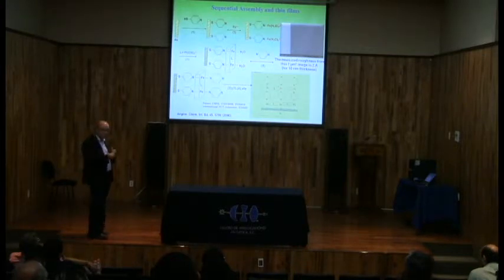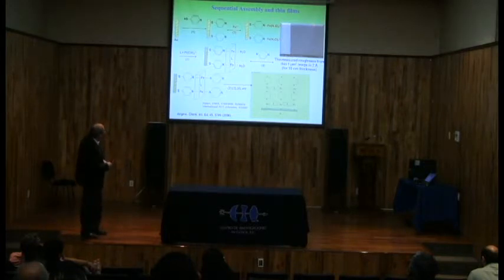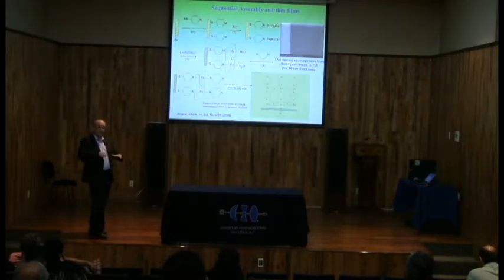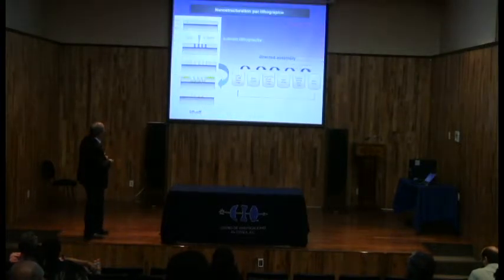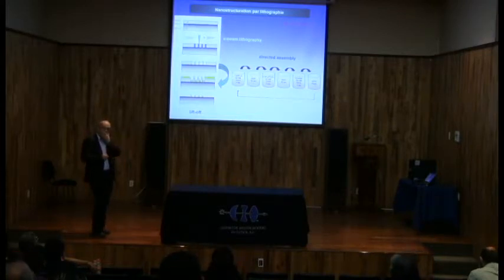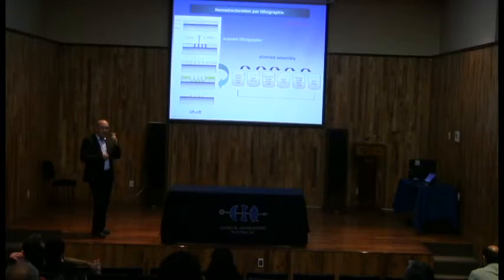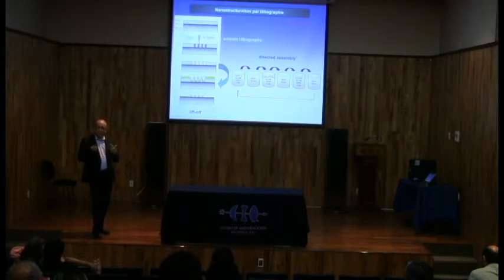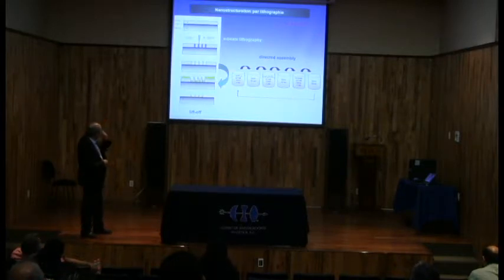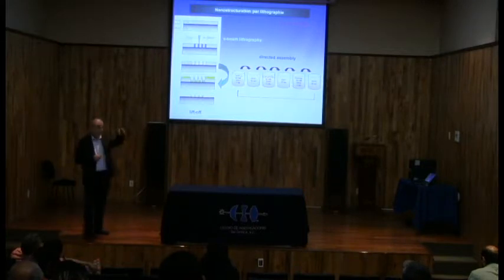And then we could also, by controlling the temperature of the film, the concentrations, etc., all the chemical parameters, we could have films with even 7 angstrom roughness. This is very nice because that means that we can have film and then we can have very low roughness for the applications, okay? So then this was also an important step, okay, in the field, because we have the thin films and we have very flat and with low roughness films. That means that we can use nanotechnology techniques to combine the layer by layer technique we have used by E-beam lithography in order to have dots, okay?